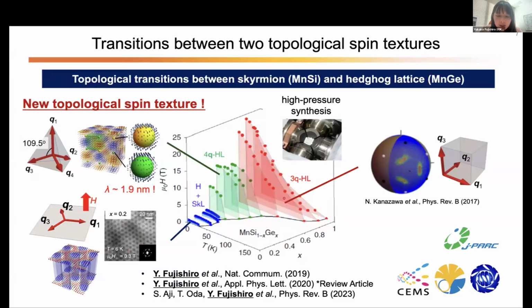And on the other hand, in a region very close to manganese germanium, we used a neutron scattering experiment to identify the conventional hedgehog lattice states, which was also reported in pure manganese germanium. But very interestingly, in the middle part of the composition region, we found a new topological spin texture using neutron scattering, which seemed to have 4 Q vectors pointing along the apical direction of the regular tetrahedron. And surprisingly, it had an even shorter magnetic period of 1.9 nanometer.